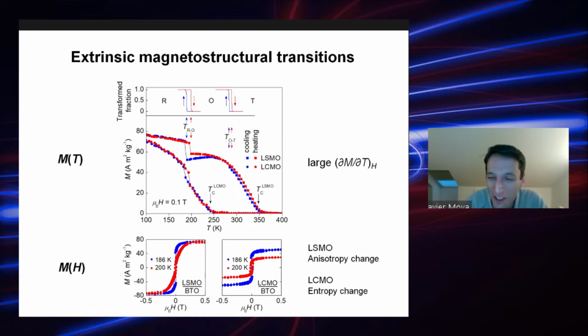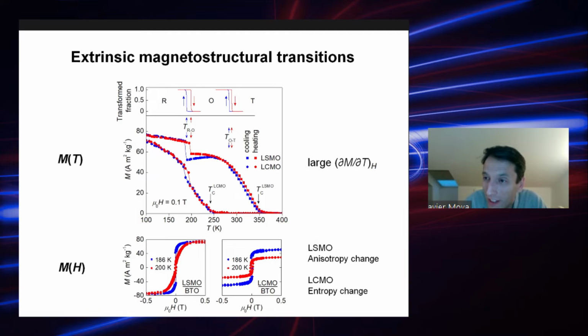Right, so when you grow manganites on ferroelectric substrates, because the strain coupling is good, you can actually create what are called extrinsic magnetostructural transitions. So in effect, what happens is that when the substrate has a phase transition, and in the case of barium titanate, which is a very well-known ferroelectric, at very high temperatures it is cubic, then at room temperature it is tetragonal, and then on cooling down, below room temperature it becomes orthorhombic, and then below 200 kelvins it becomes rhombohedral. And every time that the barium titanate changes phase, through the strain coupling with the manganite film on top, you can change the magnetization, you can control it.